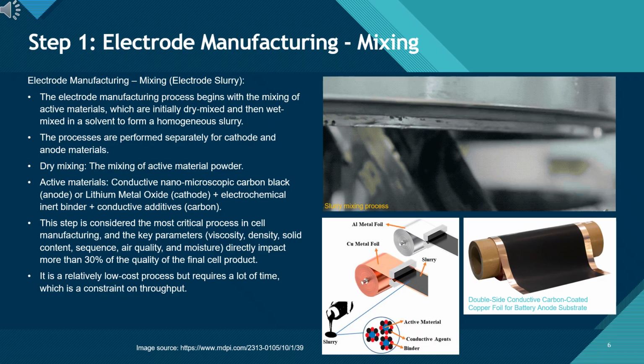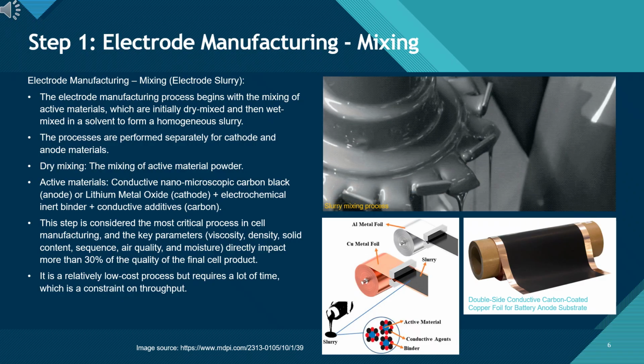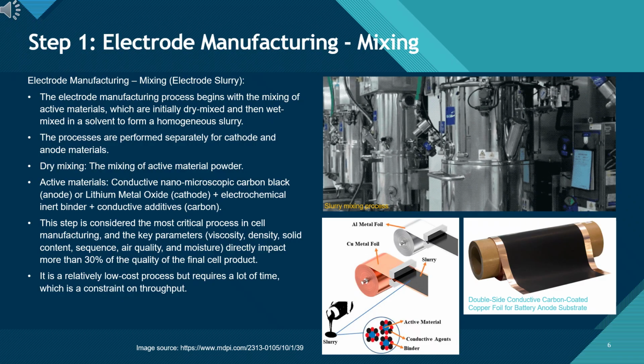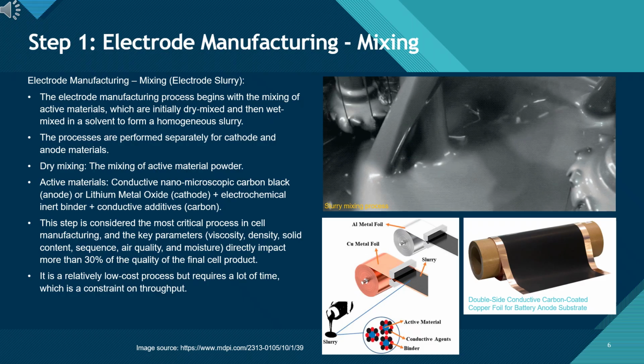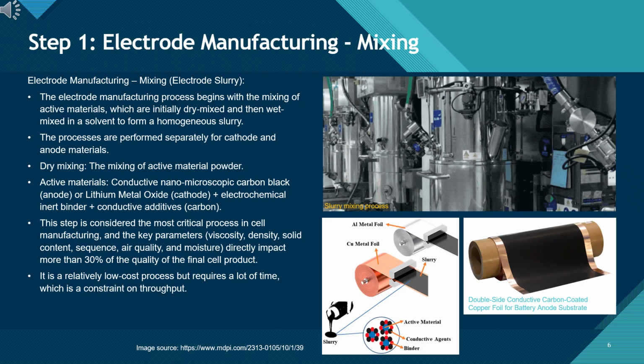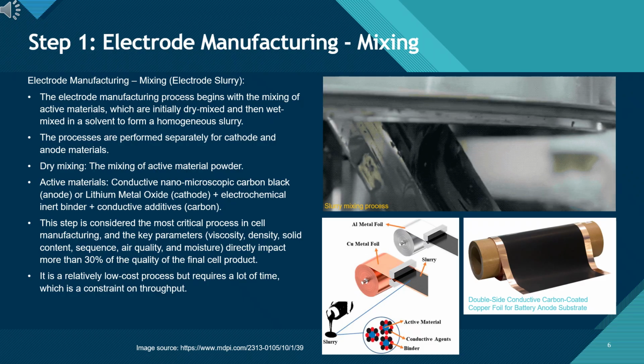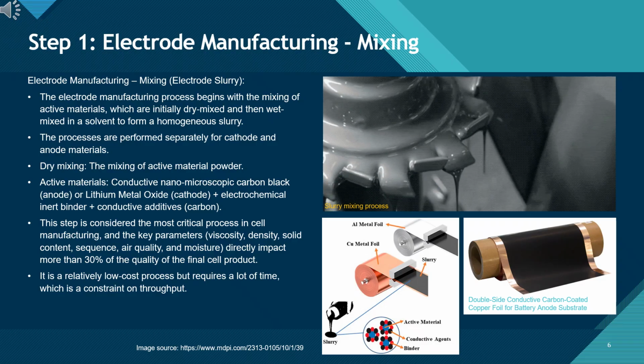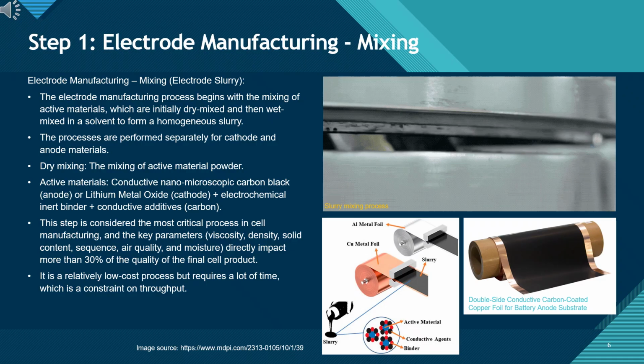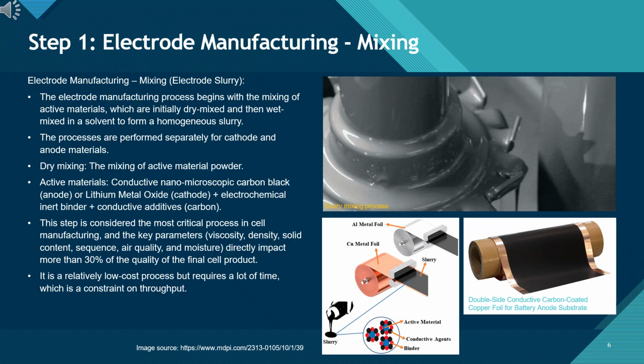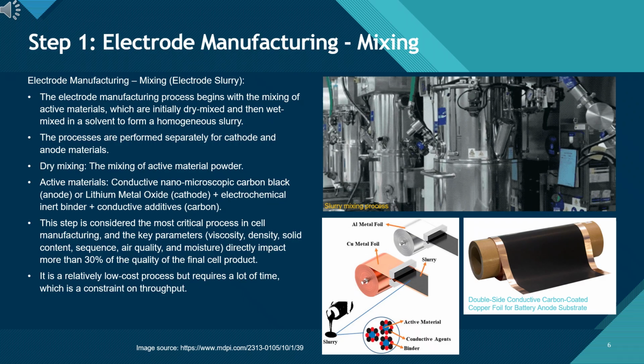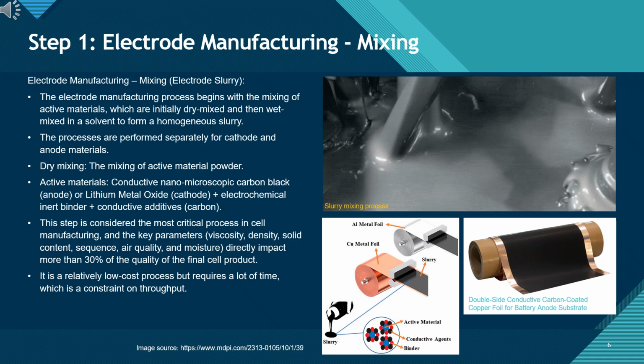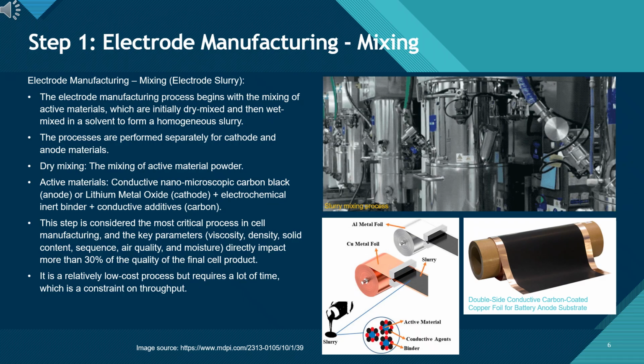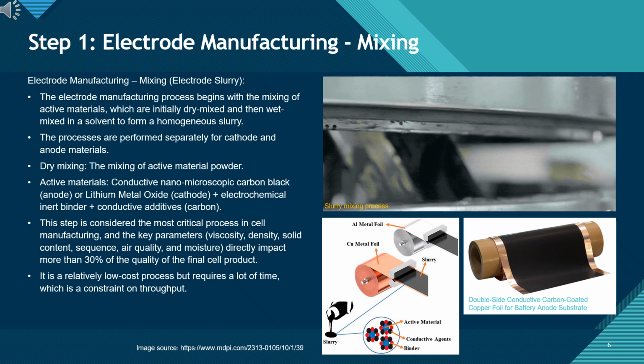Next comes wet mixing, where the powders are dispersed in a solvent inside large mixers, such as the vacuum planetary mixers shown in the picture. This turns the powders into a smooth, homogeneous slurry. The second picture shows what this looks like once coated. Here, a roll of copper foil with black anode slurry applied. The third diagram breaks down the ingredients into the active material, the conductive agents, and the binder that holds everything